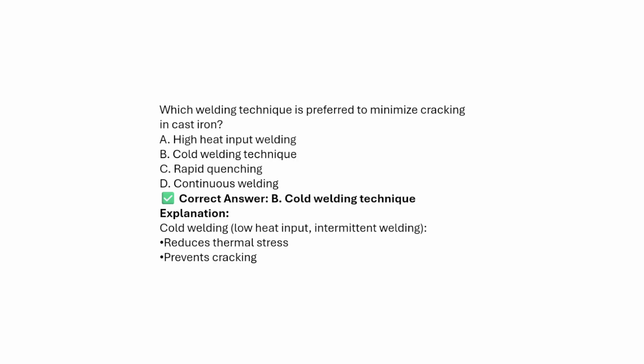Which welding technique is preferred to minimize cracking in cast iron? High heat input welding, cold welding technique, rapid quenching, and continuous welding. The answer will be cold welding technique. So cold welding means low heat input, intermittent welding, and it reduces the thermal stresses and prevents cracking.